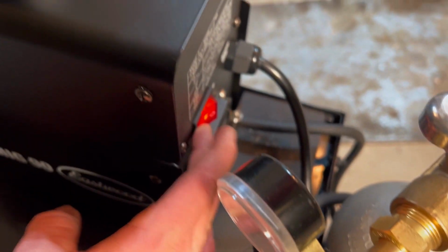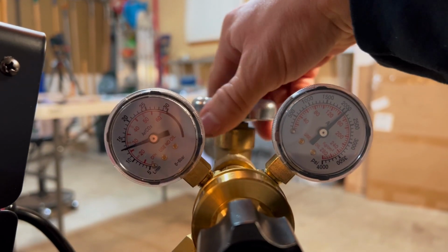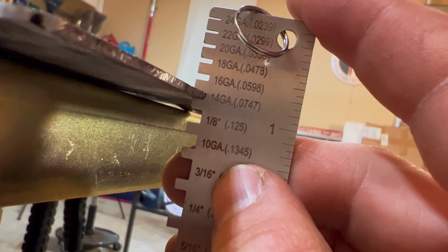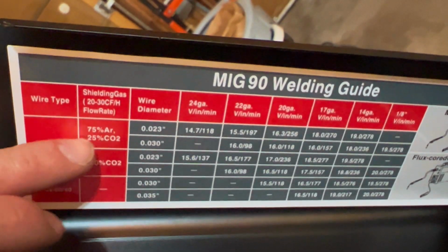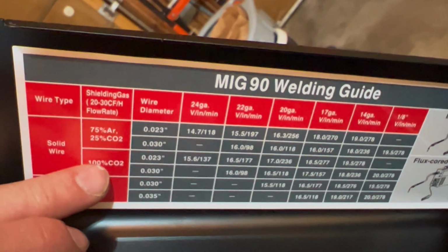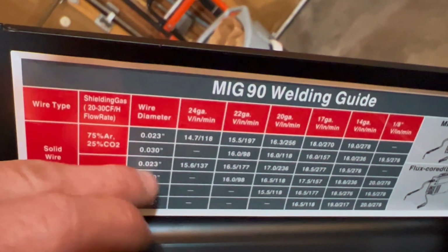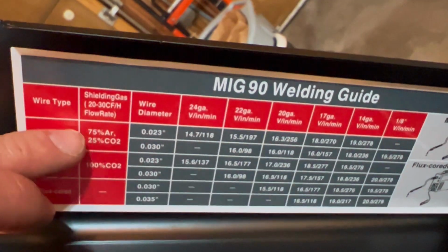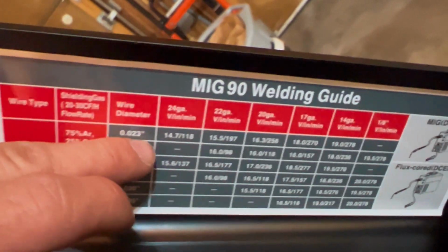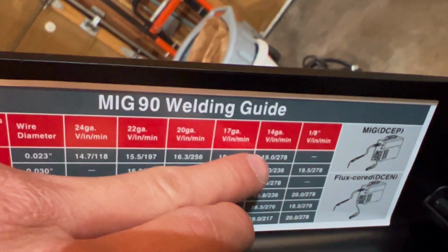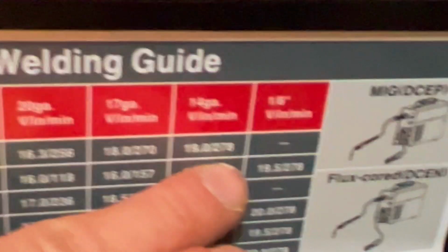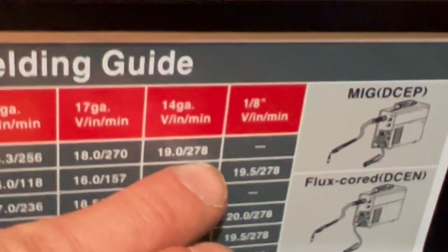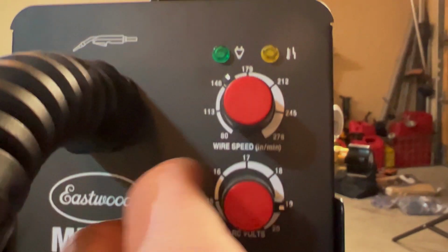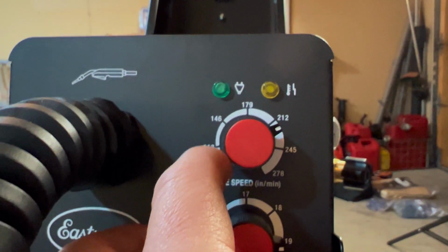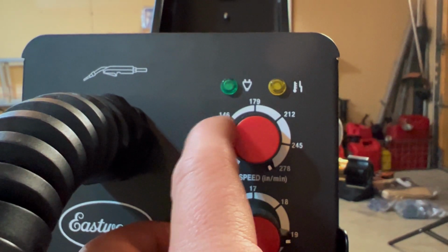And we can go ahead and power on the welder. Turn the gas on. Our workpiece is 14 gauge. And if we look at our chart, we're using 75-25. And it's cool, you can use 100% CO2 as well. It's different settings. But since we're using this and we're using .023, follow this over to 14 gauge, 19 volts with 278 wire speed. So we're getting up there pretty high. Maximum wire speed. That's because we're using the .023.